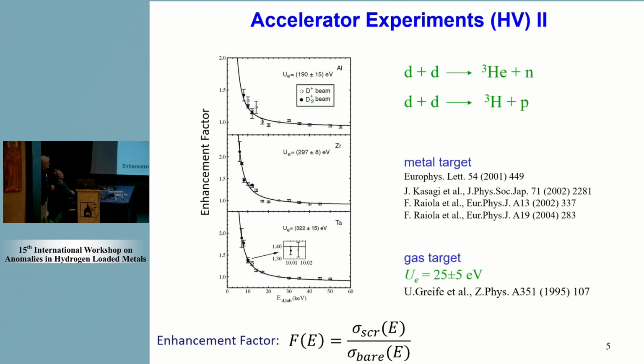And one parameter that is needed to describe it is the screening energy. The screening energy is different for different materials. It is much higher than for the gas target experiment measured before. It was 25 electron volts, and in the case of tantalum, you see here 300 electron volts. There are many other experiments made in the last 20 years, and this discussion will be made by Natalia.